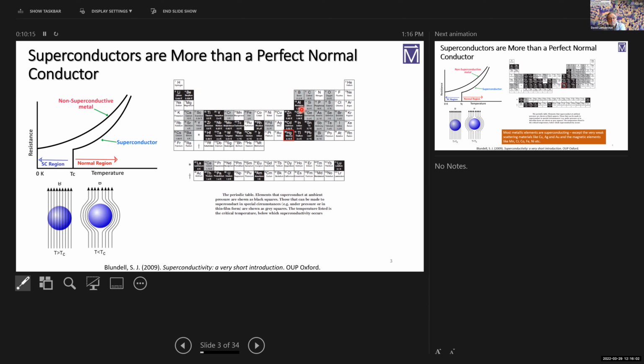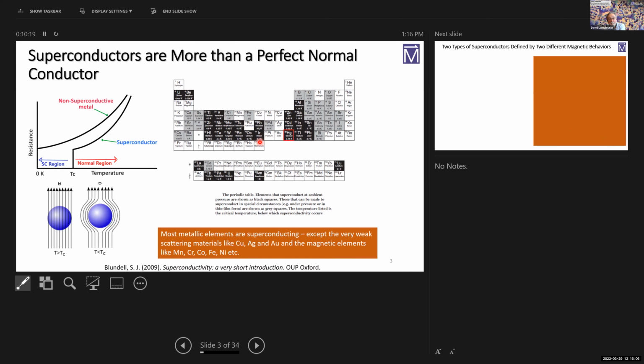But there are a good number of other materials which become superconducting under pressure. And so I think one can say that the real issue is that most metallic elements are superconducting, except the very weak scattering elements like copper, silver, and gold, which implies that there is weak electron-phonon coupling in these materials, and that's essential to the standard BCS theory of superconducting metallic materials.